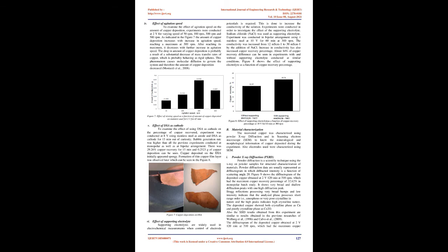As seen from Table 3 and Table 4, the copper recovery percentage removal efficiency increased with more contact time. For 1V there was no change in concentration of copper in the solution, and bubble generation rate was comparatively less. For 3V a light blackish layer was formed on top of the deposited copper on stainless steel, and for 4V complete black deposits were formed due to high potential voltage, and bubble generation rate was higher than at previous voltages. So, 2V was considered as optimum.